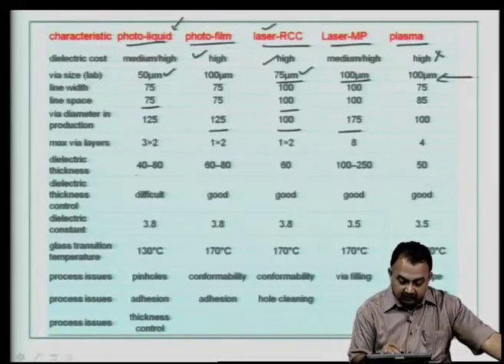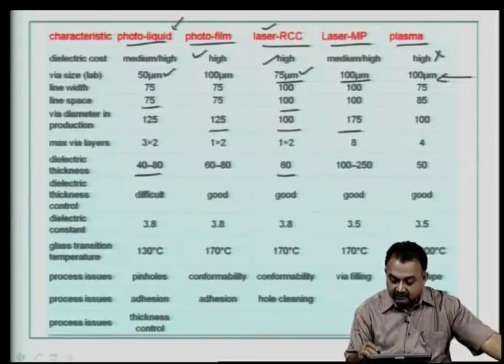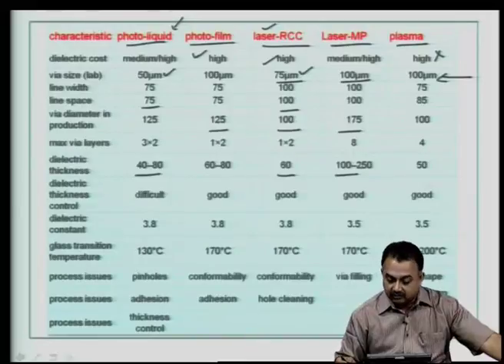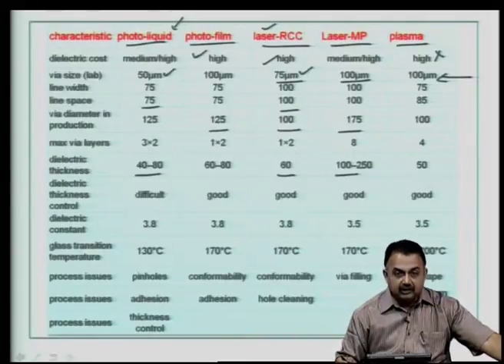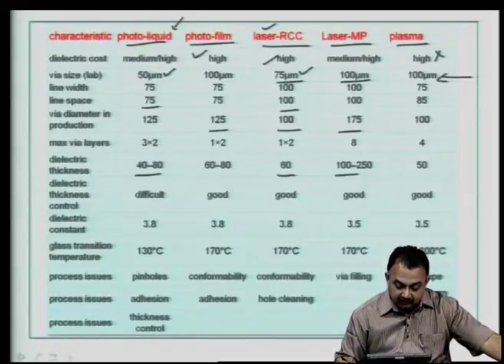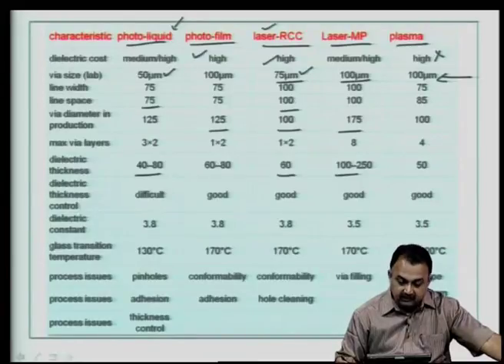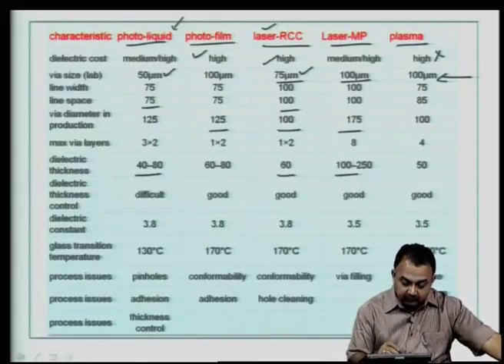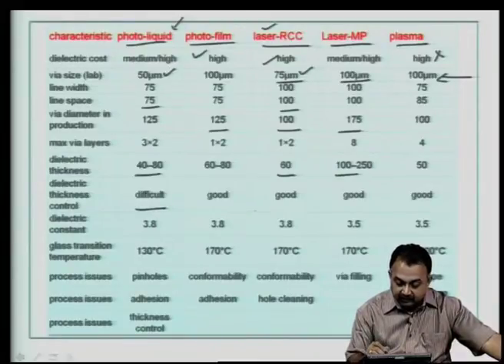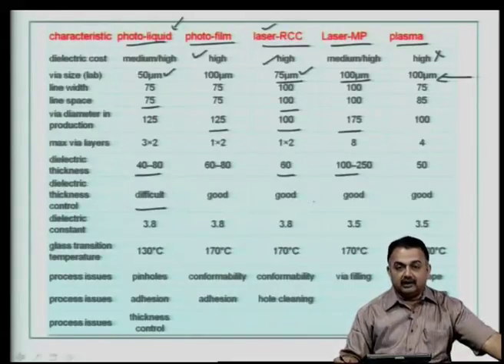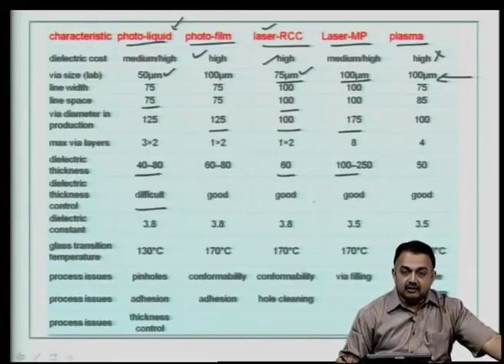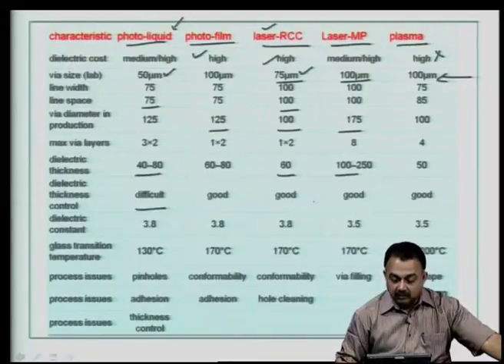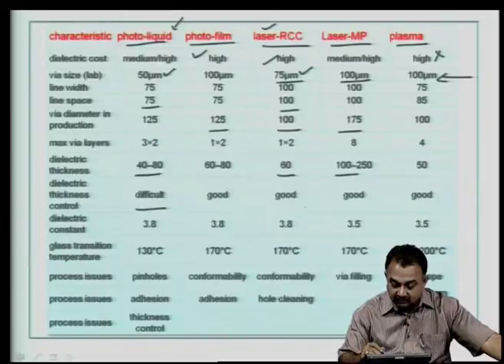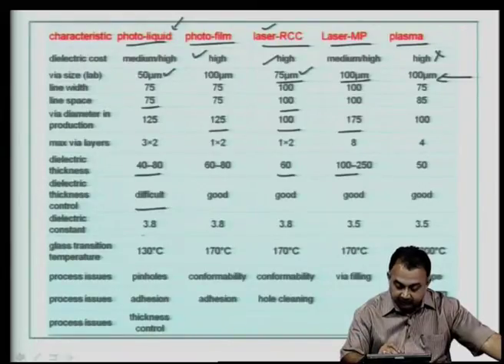Dielectric thickness varies from 40 microns to 60 microns, and in some cases it has gone even up to 100 microns to 250 microns. Dielectric thickness control, which is a very key parameter for the technicians to maintain and then understand the working of the equipment. With the liquids it is going to be very difficult, but if you get readily available substrates like your resin coated copper foil along with the dielectric material, because there are some companies which have provided standard thicknesses of dielectric coated with the copper. So, in those cases thickness control is not an issue, it is only the drilling depth that is an issue. Dielectric constant from around 3.5 to 3.8.